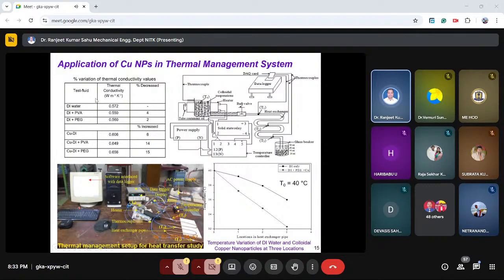And this has also been proved with respect to the thermal conductivity values. The thermal conductivity of these copper particles has been measured using a thermal conductivity probe. It has been found that the thermal conductivity of the copper particles dispersed in DI water, PVA solution and PEG solution is more as compared to the DI water. And the copper particles dispersed in PEG solution are found to be 15% more than DI water, due to the small size of the copper particles, a mean size of 6 nanometer.